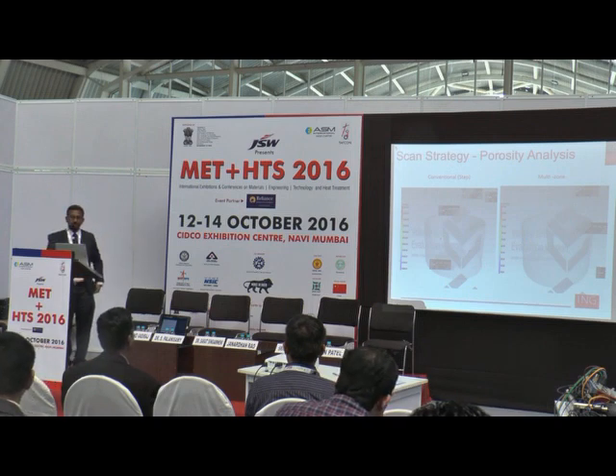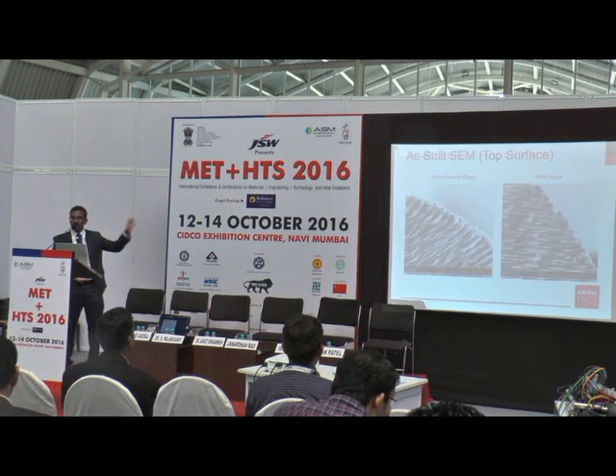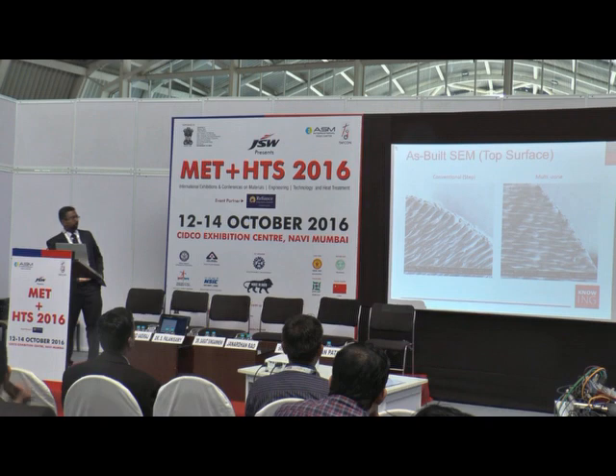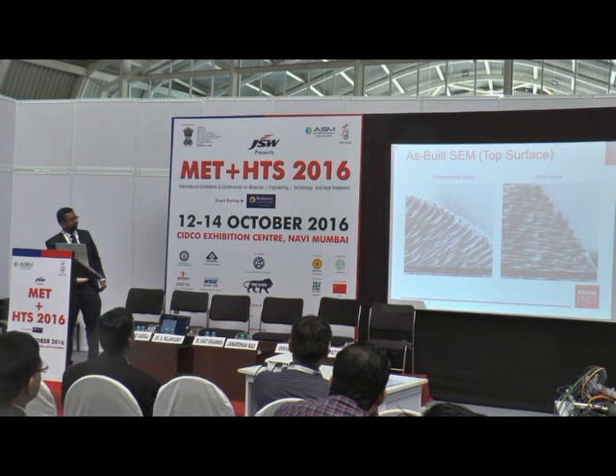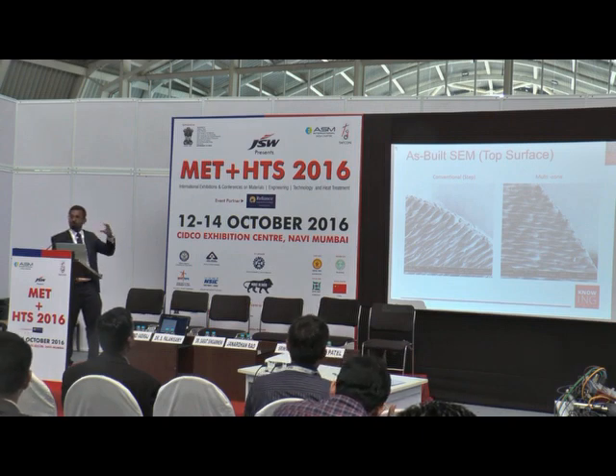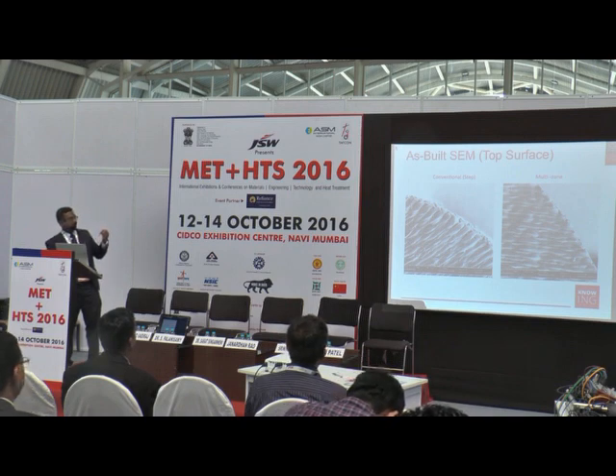Within a part, when you look at the top surface of the same sample in the same image, you can look closely here again. This particular section, the end section of the sample, you can see porosities after each scan. Layer by layer, there are porosities. The powder particle is not properly melted. When you compare to multi-zone here, at the end section, you don't see any porosities.